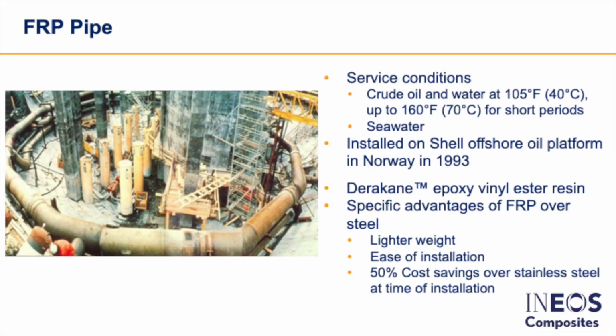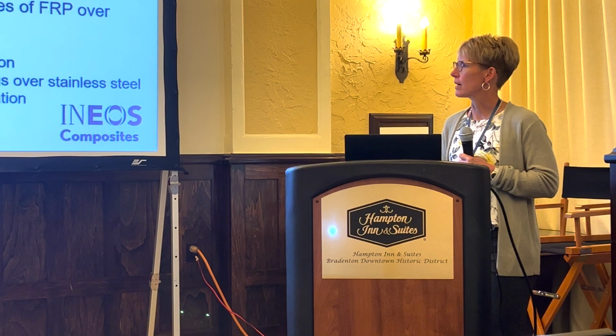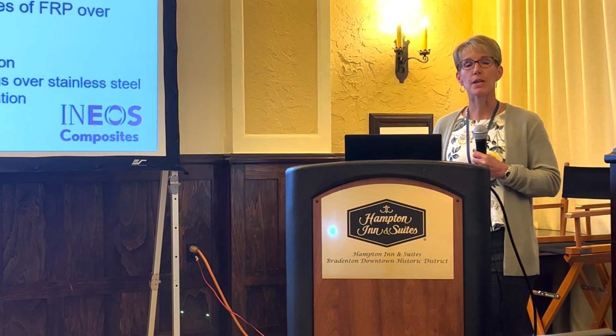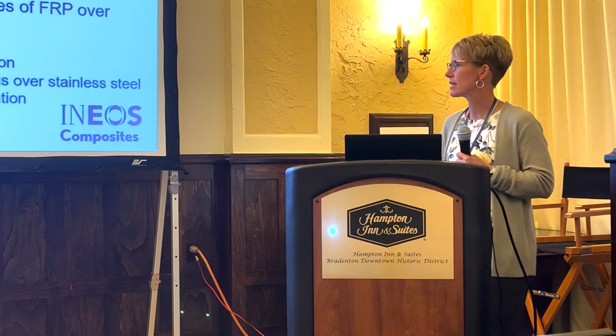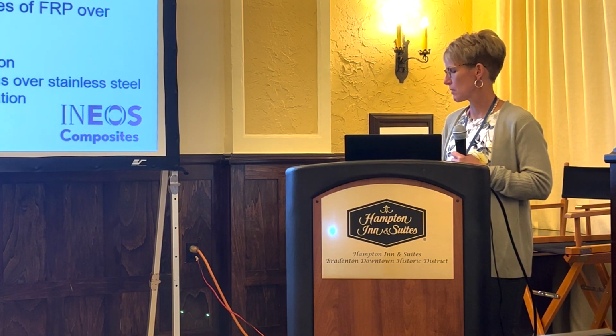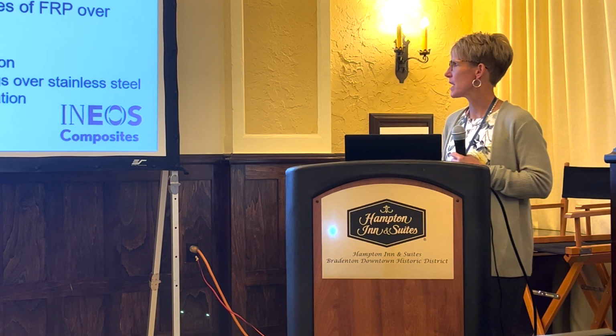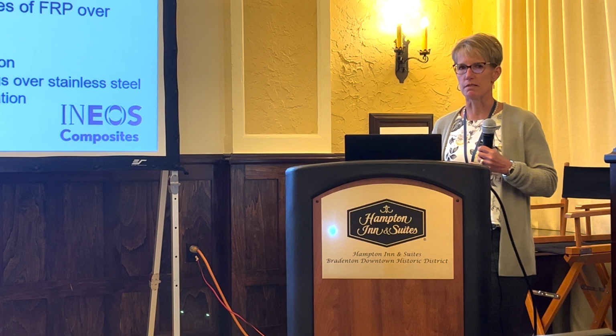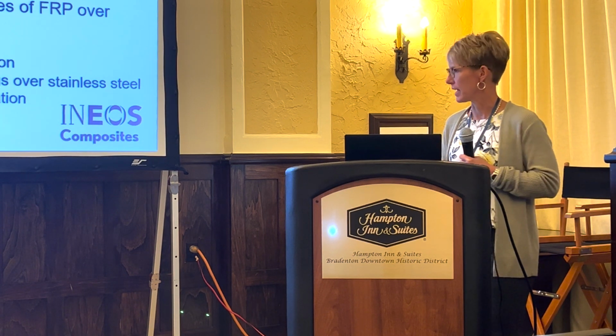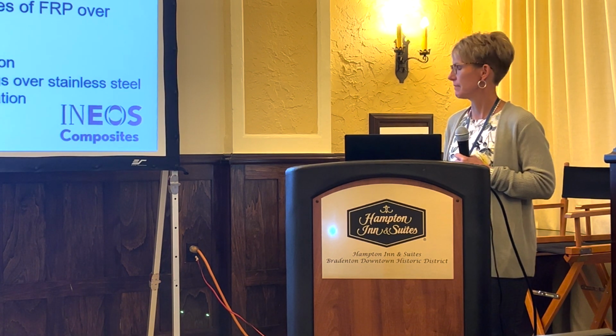This is some FRP piping that was handling crude oil and water at about 100 degrees Fahrenheit. Again, in an offshore platform, excellent application for the Derakane epoxy vinyl ester. This highlights how FRP is lighter weight, so the installation is a little bit easier, and at the time of this installation, it was estimated that there was a 50% cost savings over using steel, just because of the decrease in the weight and the ability to install this.